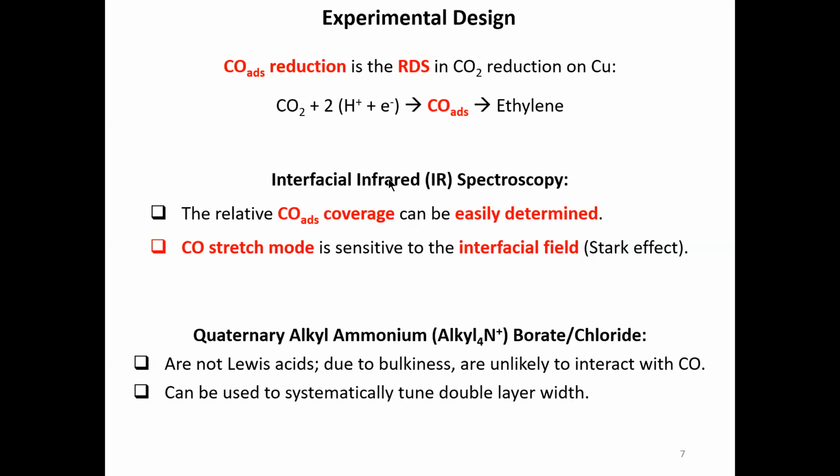Importantly, with infrared spectroscopy, we can relatively straightforwardly determine the relative CO coverages in the presence of different cations. And equally important, with infrared, the CO stretch mode of surface-adsorbed CO is sensitive to the interfacial electric field strength. So with this intermediate, we have a direct molecular probe of the electrocatalytic interface.